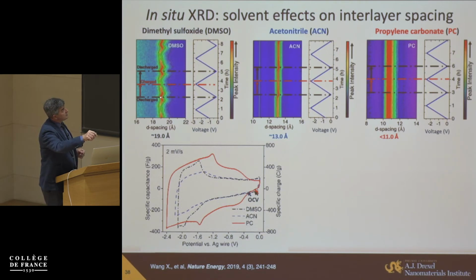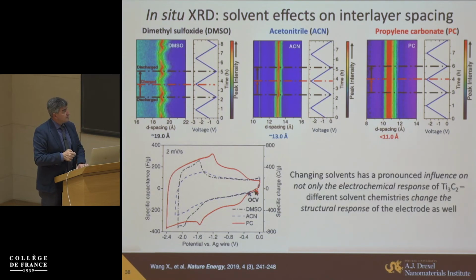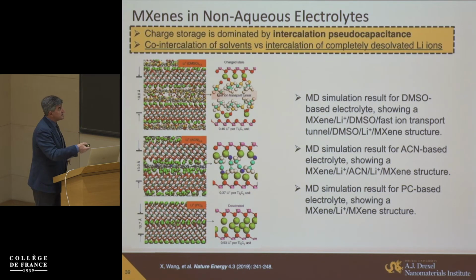Moreover, there are relatively large fluctuations of spacing with charge in DMSO. There are some fluctuations in acetonitrile, and it's very stable in the case of PC. So what just happened here? You cannot predict behavior based on the behavior of bulk electrolyte, or on what we know, for example, for porous carbon materials, for example, capacity. The reason is very simple.